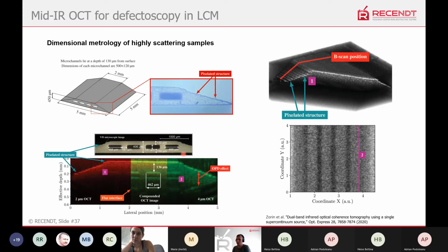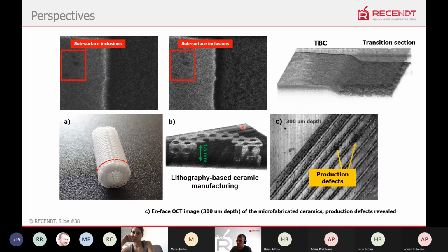And the field in which we work now is some additive ceramic manufacturing, where we apply mid-infrared OCT, and here it performed quite well. Actually, the resolution of such a 3D printer, which prints such samples, is around 35 microns, so it's nearly the same as our first mid-infrared OCT version, and that's more than enough for quality control and assurance of this technology. And we are working on this field currently. It's just some other materials that can be probed. So this is also 3D printed ceramics, which are quite fancy samples. Also some thermal barrier coatings to find some inclusions, and as I said, just a normally sintered ceramic sample.